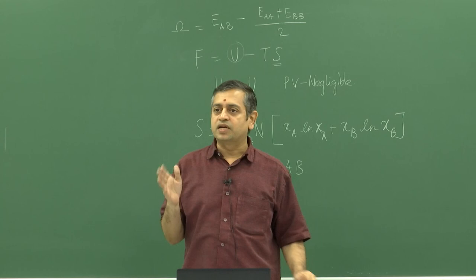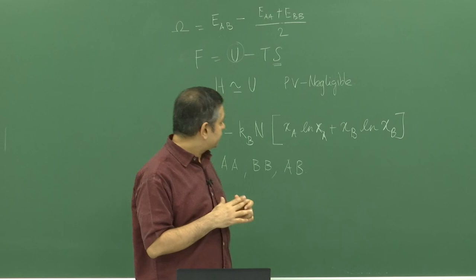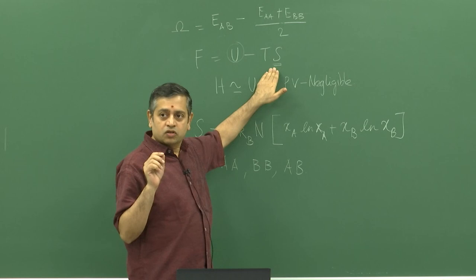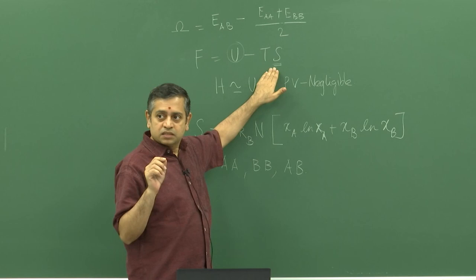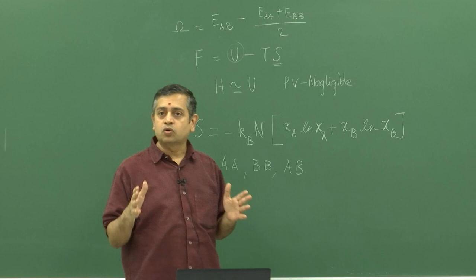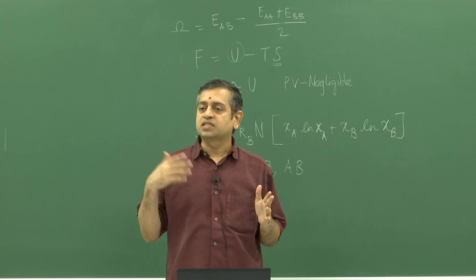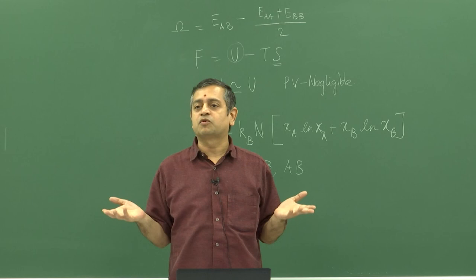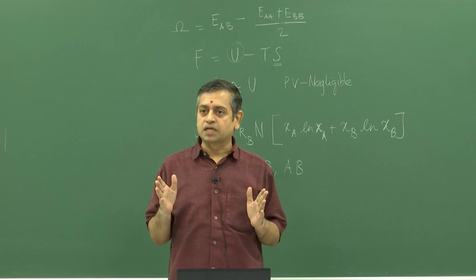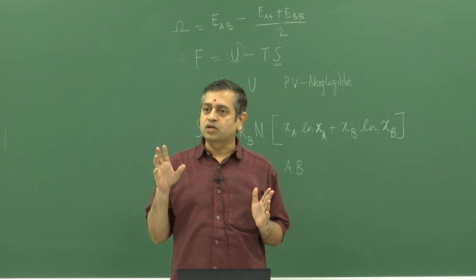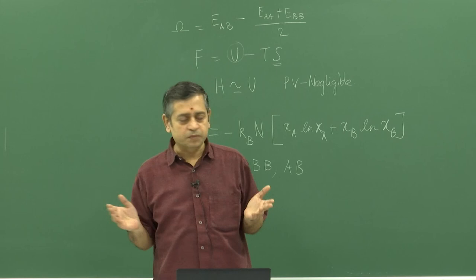And because it is evaluation of entropy, you can also see that if you do only molecular dynamics simulations, the entropy that you will get will be only the vibrational entropy, because molecular dynamics does not go to time scales where diffusion is possible. If diffusion is not possible, configuration is not going to change. If configuration is not allowed to be explored, you cannot get information about the configurational entropy. Okay? So typically MD simulations will give you the vibrational entropy contributions. You have to do Monte Carlo if you want the configurational entropy contributions. Of course, you can do both and get both entropies, from which you can evaluate the free energy.